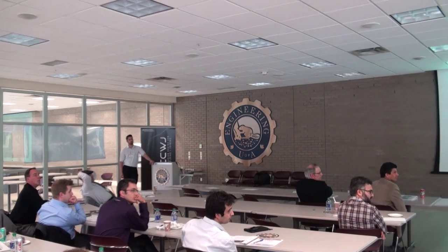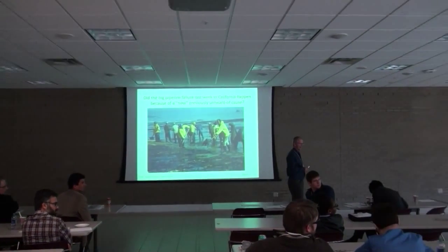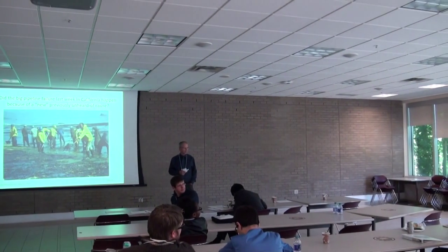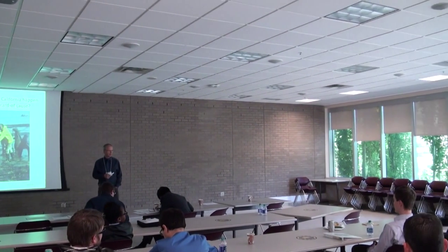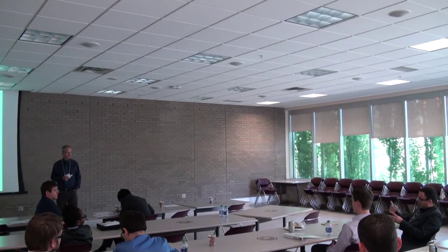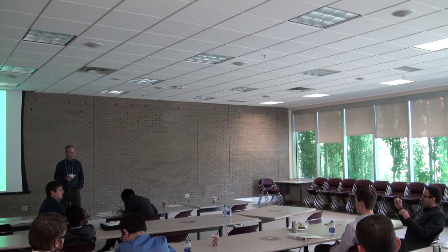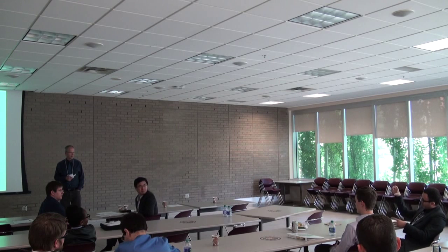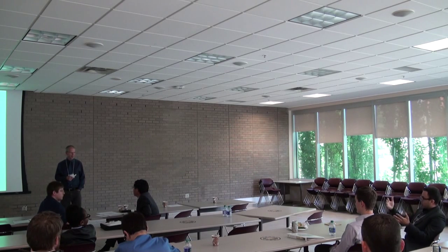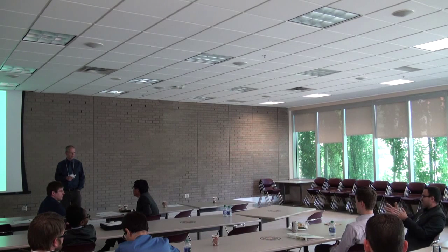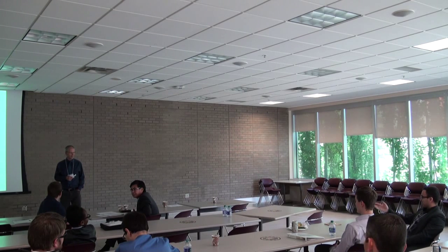I just have a comment. It's not regarding carbon steels, but I was working at Suncor, and we were welding 4-inch thick, 14-inch Inconel piping on a hydrogen furnace that's been in service since the 60s. We finished it up. We rooted it, hot passed, they x-rayed it, it was good. We filled it up, did an LPI, and there were linear indications around the site. We started digging it up, LPI again, all the way down to the root, four inches deep. It had cracked right through. We ended up having to do a back step procedure to minimize the shrinkage and distribute the heat, and it took us 2 weeks to weld.